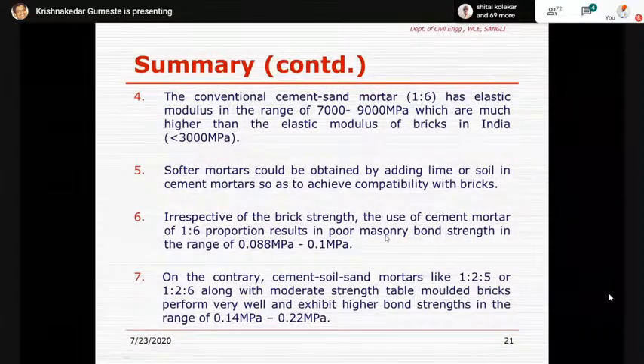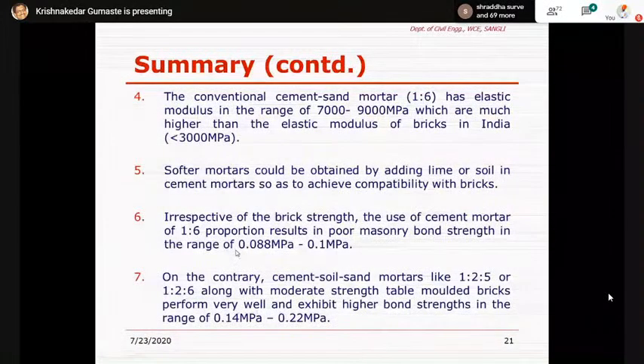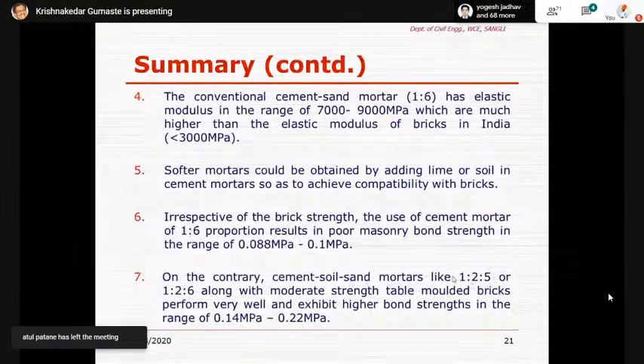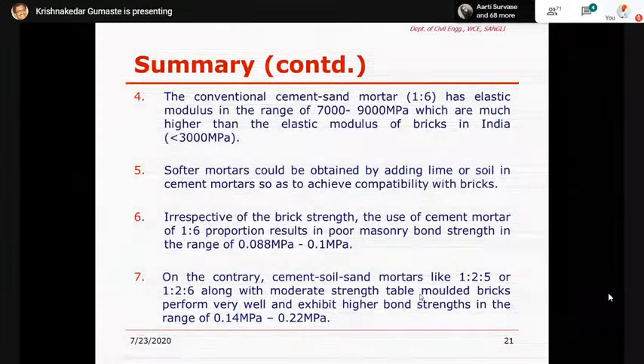is observed to give poor masonry bond strength in the range of only 0.08 to 0.1 megapascals. On the contrary, combination mortars like cement, soil, sand mortars like 1:2:5 or 1:2:6, along with moderate strength table-molded bricks, perform very well and exhibit higher bond strengths in the range of 0.14 to 0.22 megapascals.